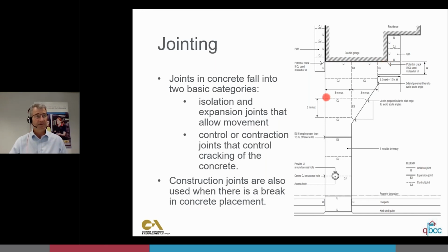And a good example here on this control joint, where instead of going right across to this edge in a straight line, you've come to this edge in a perpendicular way. The reason for doing that is you've avoided making a sharp angle that might cause a point where it might crack. So really important to get this joint detail correct, just to make sure that you get a nice looking product at the end.